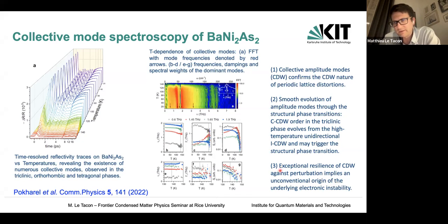But the funny part is that it shows an exceptional resilience against perturbations, meaning that they change the fluence and they always find that they are not able to destroy the charge density wave. And they again concluded there that the CDW is highly unconventional in nature.